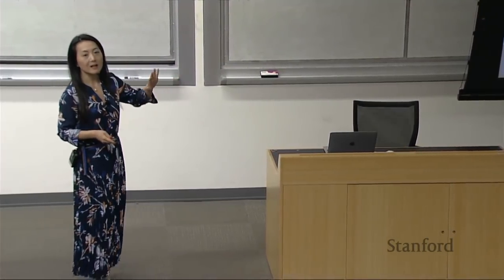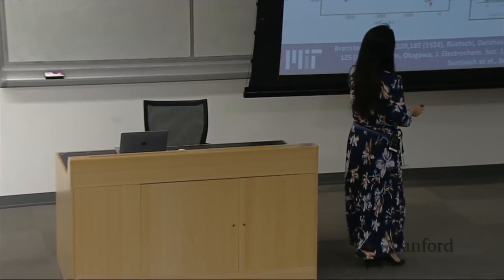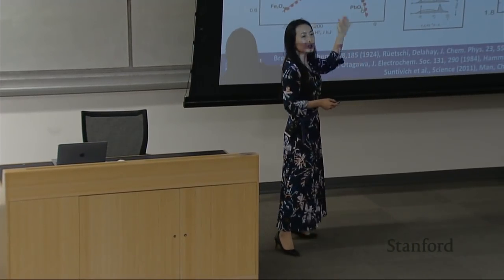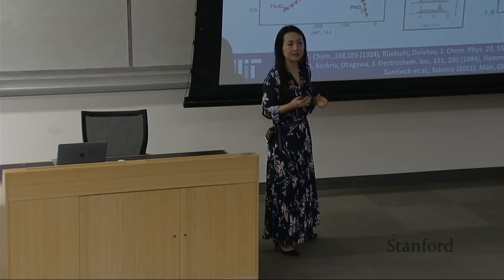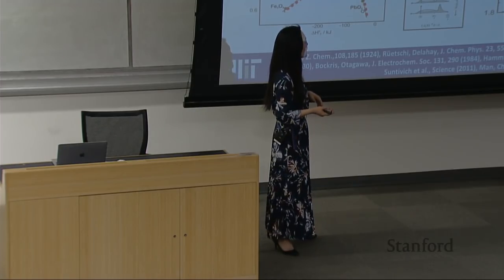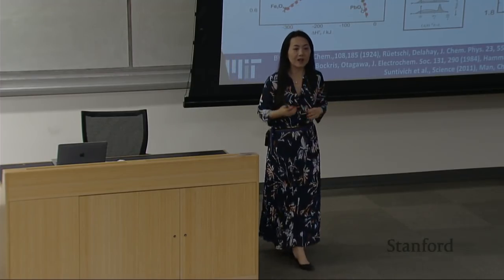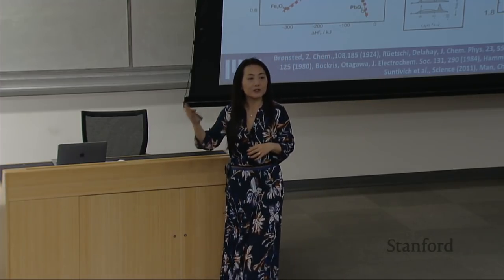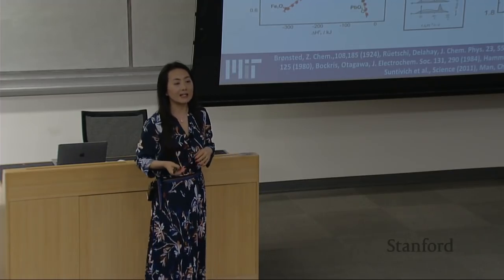Over the past 100 years, many researchers have looked at how to draw a relationship between activity descriptors, or some parameter that may influence activity, with the reaction kinetics. For example, there's the work of Jens Norskov correlating the d-band center, or electronic structure, of metal surfaces to binding of different reaction intermediates, through which they can develop reaction mechanisms and screen different surfaces that can have high or low catalytic activity.